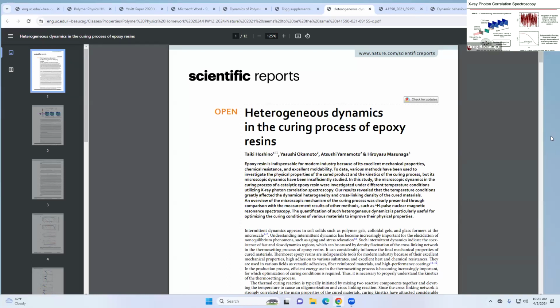So from this function, we can actually fit it and calculate what the relaxation time is of that process, right? So when you do that and you measure the relaxation time, you're basically looking at the diffusion or diffusive behavior of that particle on the nanoscale, right? So you do all this work, and essentially all you get out is this time scale that tells you how fast that particle is diffusing in the nanometer length scale. So that's why I basically say we're measuring particle diffusion in that complex fluid, just like we are in dynamic light scattering. But here we're looking at things on the order of 1 to maybe 100 nanometers, something like that, right?